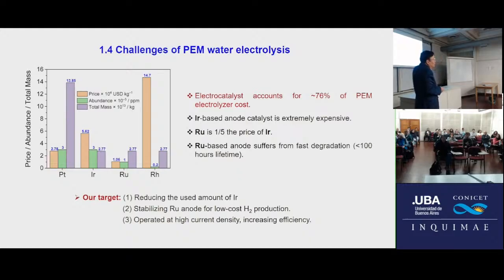In the last 6 months, 3 papers were published in Science. One paper is Japanese; they say we can reduce the amount of iridium used. The second one uses ruthenium; the price is much lower, but the stability is not so good. So the Chinese college says we can use less ruthenium and operate for a very long time. Another Science paper also. So very important, we need to consider reducing the amount of iridium. Second, make the ruthenium catalyst very, very stable. The third one is we must consider operating at a high current density.